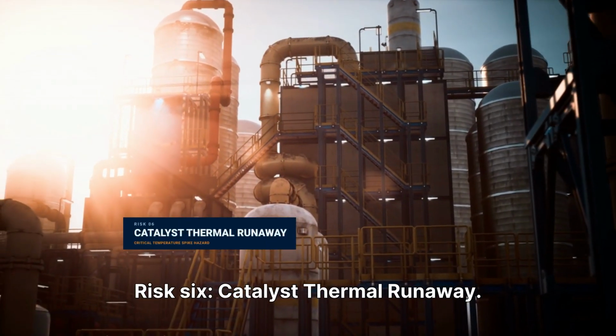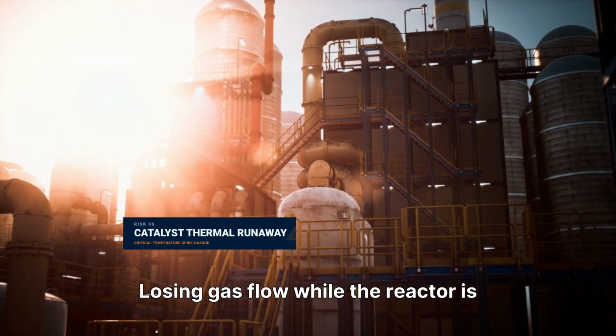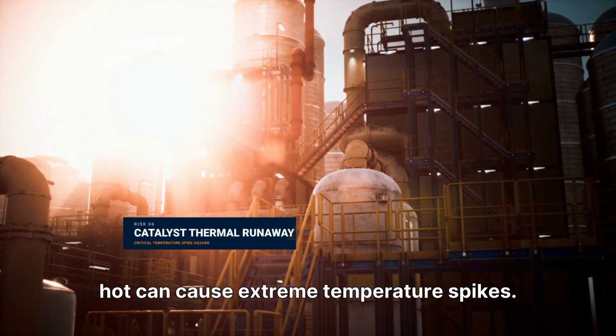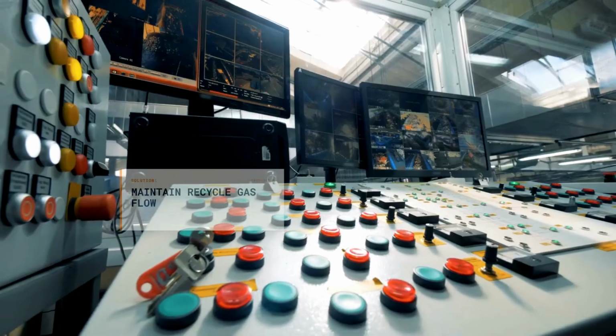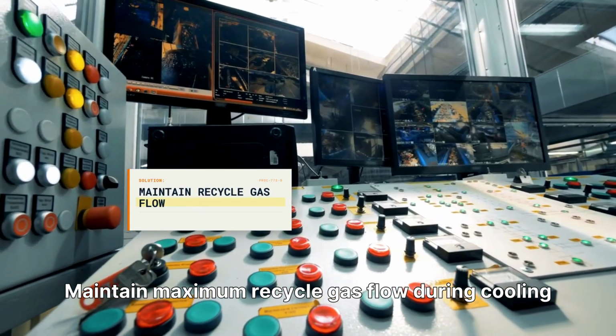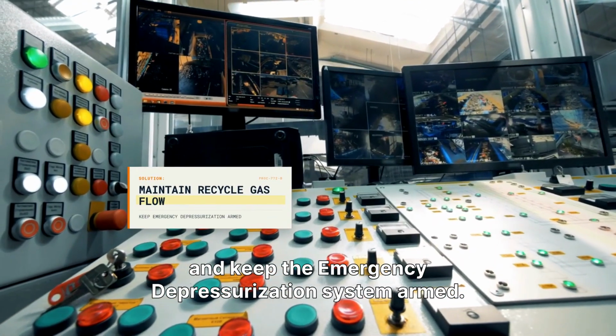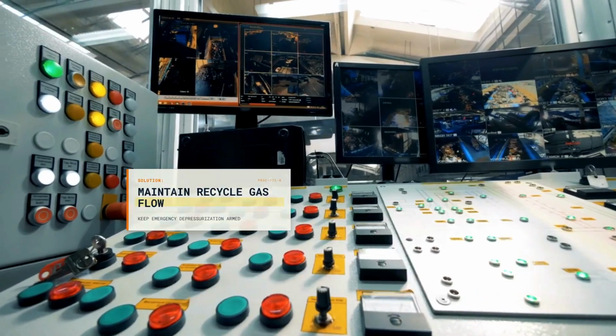Risk 6. Catalyst thermal runaway. Losing gas flow while the reactor is hot can cause extreme temperature spikes. Maintain maximum recycle gas flow during cooling and keep the emergency depressurization system armed.